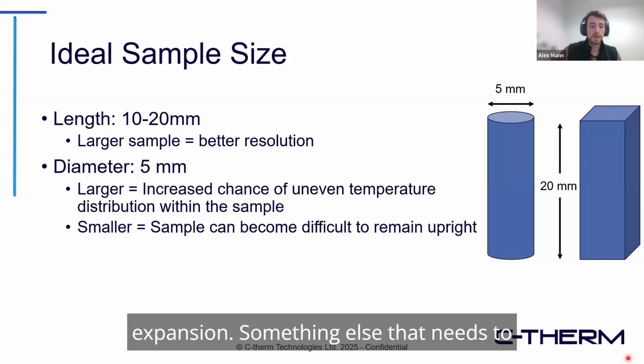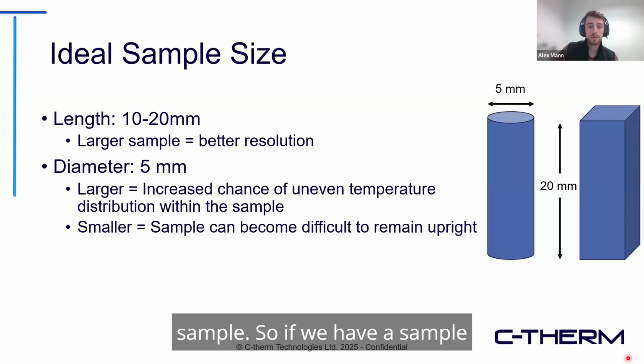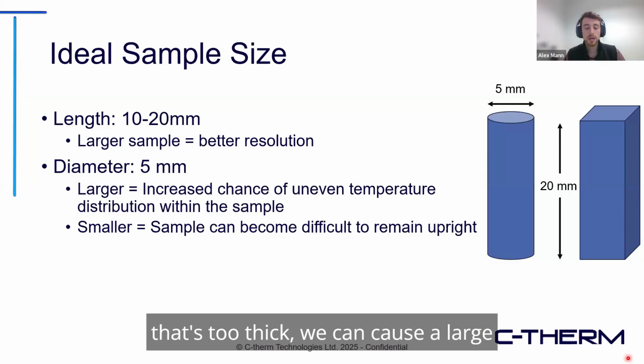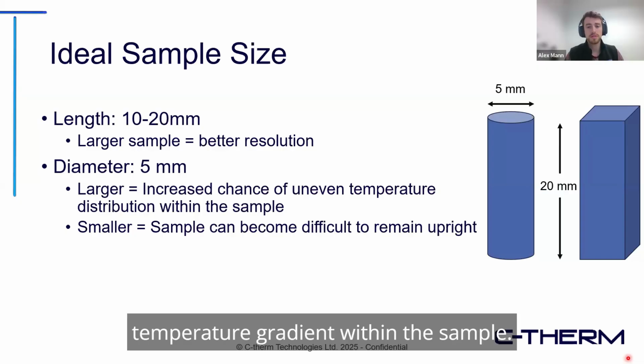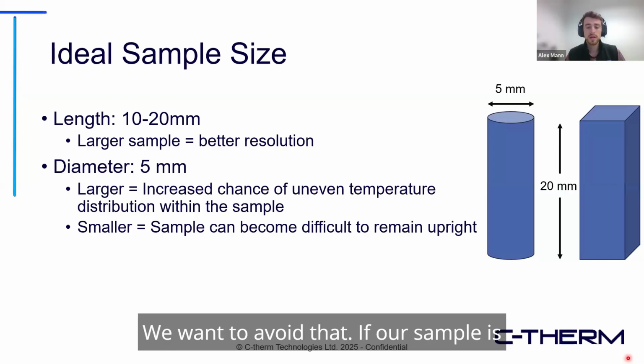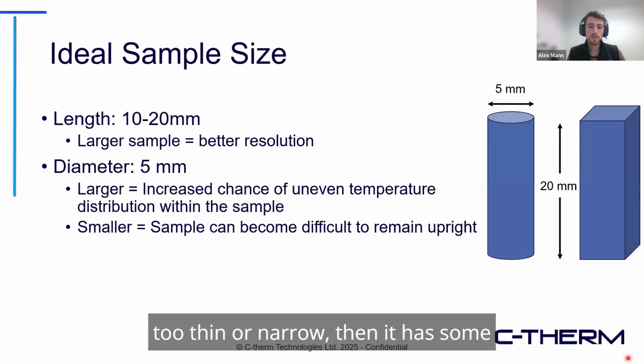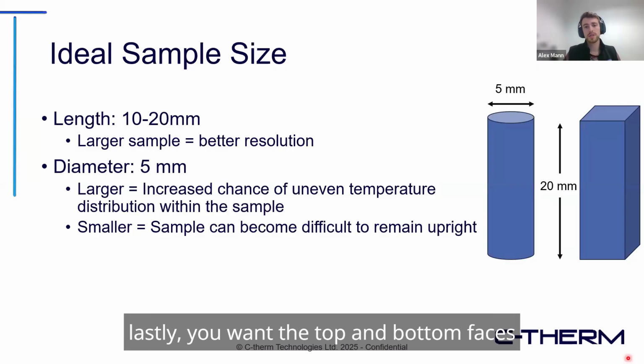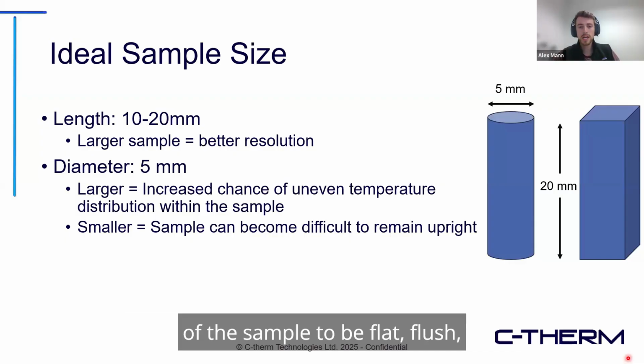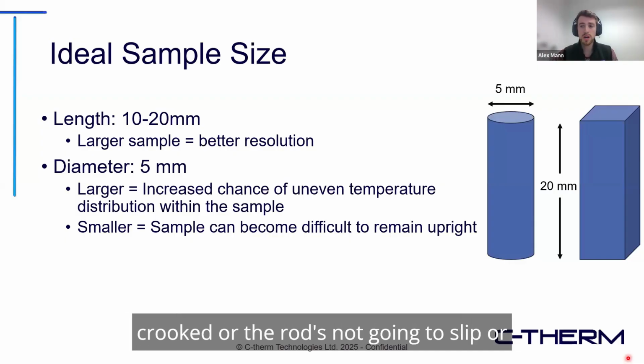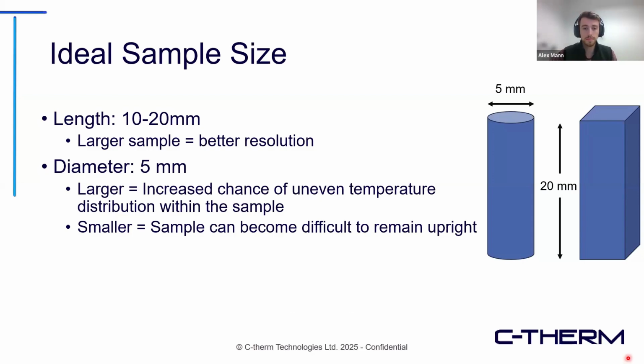Something else that needs to be considered is the diameter of the sample. If the sample is too thick, we can cause a large temperature gradient within the sample, and we want to avoid that. If our sample is too thin or narrow, it has trouble standing up on its own. And lastly, you want the top and bottom faces of the sample to be flat, flush, and parallel, so that the sample isn't crooked and the rod isn't going to slip or slide.